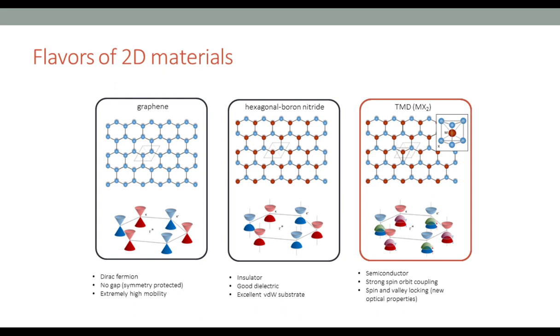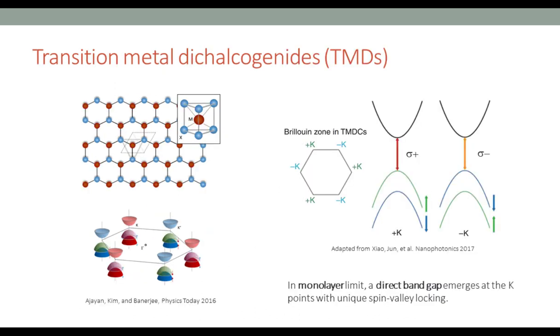And then finally is the TMD, which is a semiconductor. And when reduced to the monolayer limit, it actually has a direct band gap. This is the material that we're going to be focusing on today, the TMD class. So what are TMDs? They are transition metal dichalcogenides. They're named because they have a transition metal in the center, and they have two chalcogen layers above and below. That constitutes one layer. And this single layer has a direct band gap at the K points in the momentum space. These K points are locked to both spin and circular polarization. So what this allows us to do is use circularly polarized light to address individual valleys and therefore individual spin excitons, which are quite exciting.